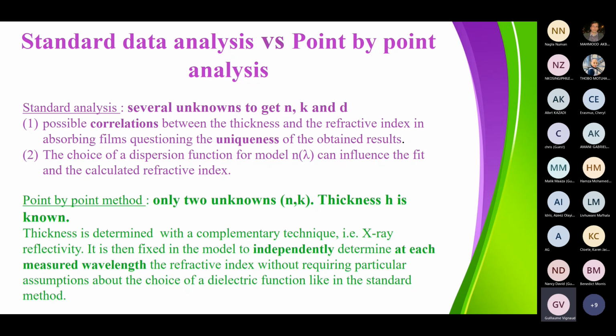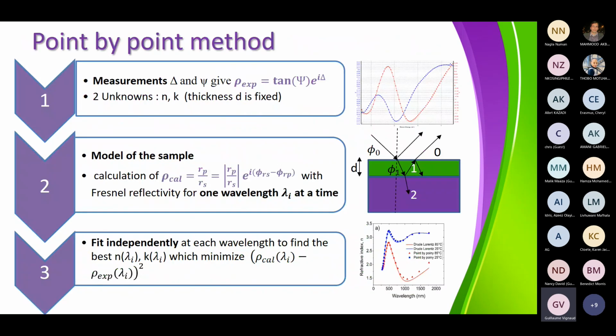Okay, then in the point-by-point method, the advantage is first you measure Psi and delta, as in the previous method. You also calculate the experimental rho. This is the same method. You still define the model for the samples, and then you calculate the ratio, but you calculate the ratio for one wavelength at a time, and you obtain the corresponding N and K without a dispersion law. For each wavelength, you make a fit, and you obtain the value of N and K. Then there is no correlation, and there is no dispersion law to define. This is the advantage of this approach.